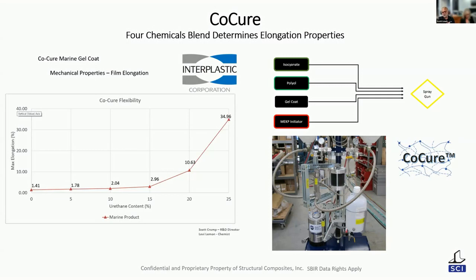The urethane we're adding for coatings is expensive. It's automotive grade aliphatic urethanes. It's got to be out in the sun. So if we're making a co-cure resin, we can go to aromatic resins instead of aliphatics and drop the cost a lot. But here we're in a coating system, so because that's expensive, you're going to optimize the cost. But as you increase urethane content, you can see elongation radically changes. And you'll see in the next slide, we're up over 50% now in other studies. And we're looking at blends very, very high so that we can have this wide range of properties.